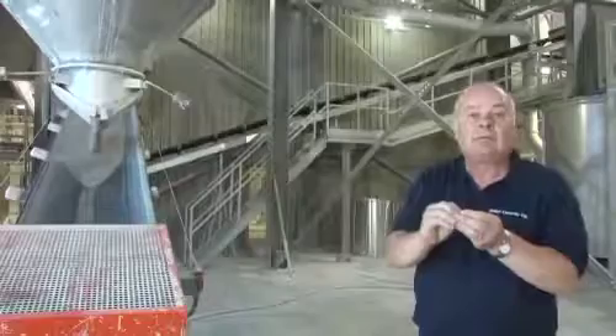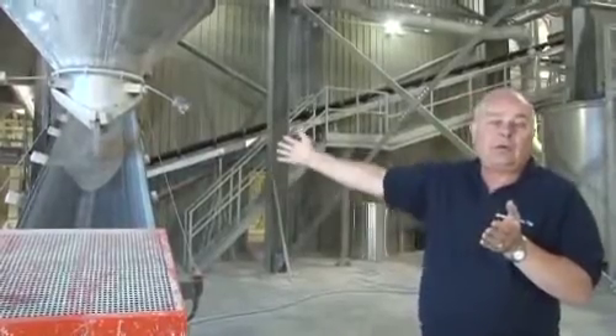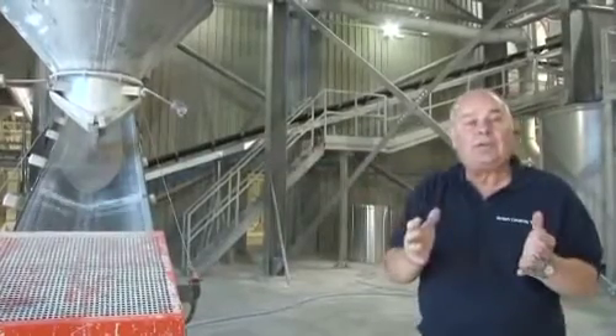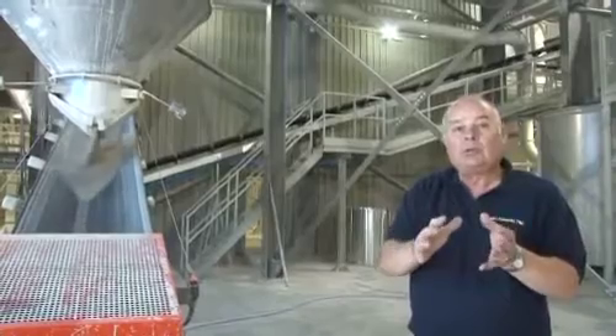This dryer will produce in excess of 30 tons an hour with a moisture retention of 5%, which is needed for when we compact the tile. The powder now will go into storage, where it will stand for 24 hours before we use it, to allow it to get more homogeneous. We've produced the powder, and what we're going to do now is compact that powder and make it into a tile.